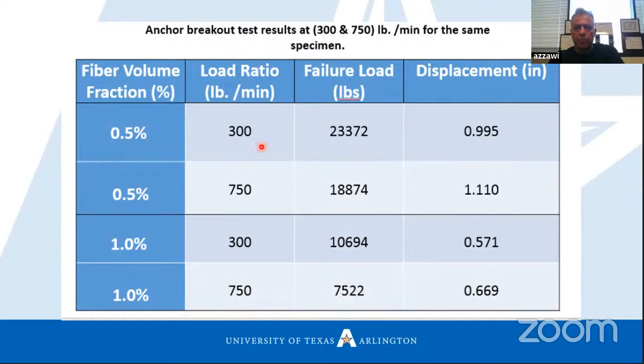For both loading rates, 300 and 750 pound per minute, as we see, for example, with the 0.5% steel ratio, 300 pound per minute gives us 23,000 pound. 750 gives us 18.87 thousand pound. Also for 1%, we did the same thing. So increasing the loading rate will reduce the failure load, and also will increase, as we see here, the displacement.